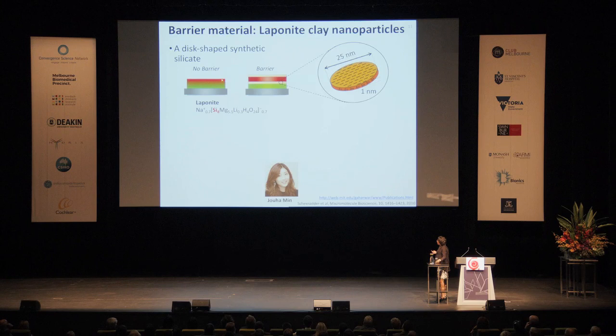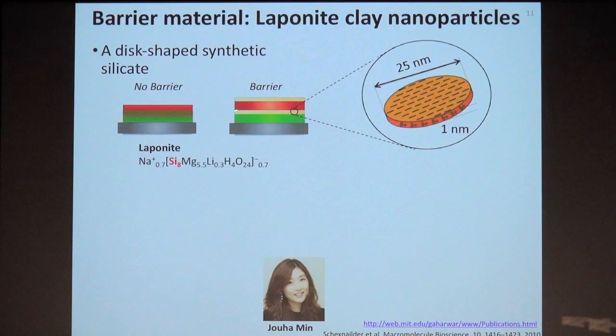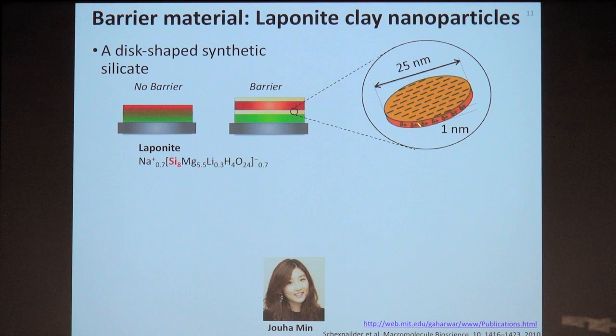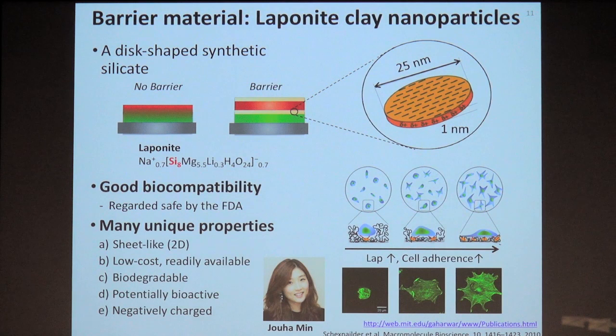Now, she wanted to control the relative rate at which the gentamicin sulfate, which is the antibiotic that she's using, appears, and the BMP2 appears. And to separate them a little bit more, she introduced these little nanolayers that contained clay. And the clay is this disc-shaped, silicate, coin-shaped material. It's biocompatible, generally regarded as safe, and it actually increases cell adhesion properties. So she thought she could use essentially these as kind of diffusion barriers so that it takes a little bit longer for the BMP2 to degrade and come out of these films.